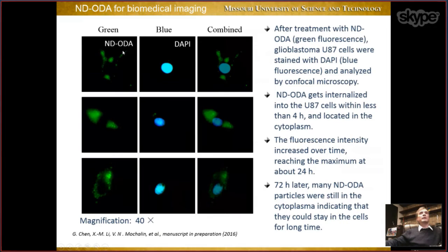We already demonstrated that if you put it in contact with cells, ND-ODA accumulates in the cytoplasm, and here you see this green confocal microscope image. This comes from ND-ODA. When we stain the nuclei of the cells, we can clearly see that nanodiamond does not accumulate in the nuclei. Okay, so this is where the nucleus is, and we can prove it by using a specific staining agent for the nucleus. And nanodiamond stays in the cytoplasm. So this opens up additional opportunities for this nanodiamond to be used for biomedical imaging.